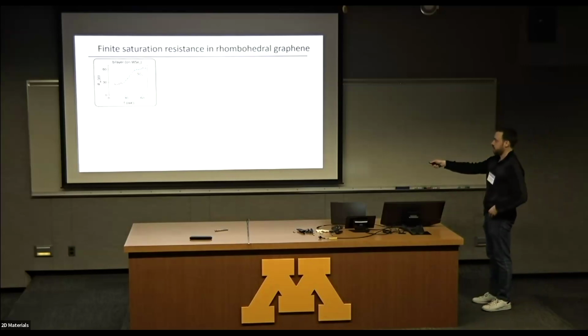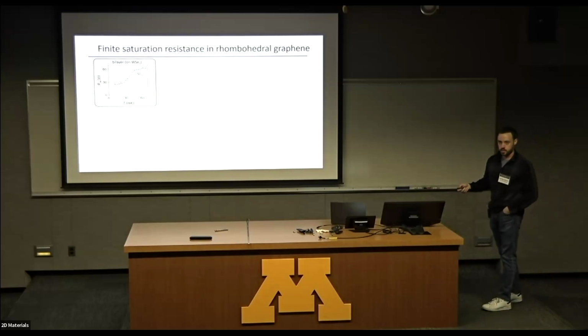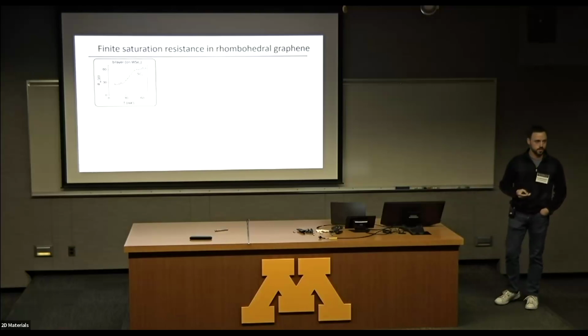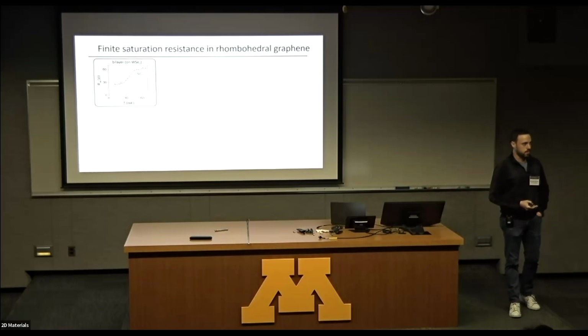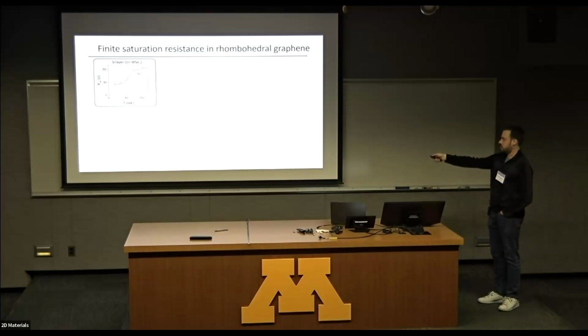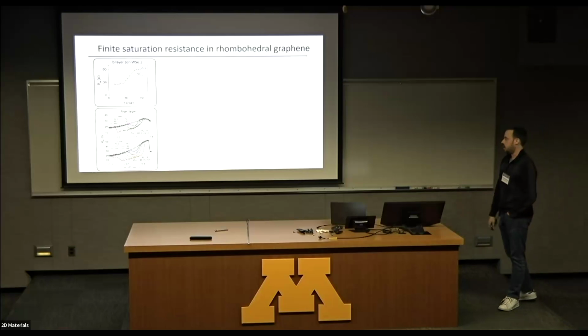There's measurements of, say, bilayer graphene on WSe2, where you have what looks like a superconducting transition, but the resistance gets stuck just below 30 ohms. This is an ultra low critical temperature, and if you've ever tried to cool electrons to below 30 millikelvin, you'll know that it's not easy. So maybe in this system, the electrons were just not getting cold enough. But we can look at other samples, and in a 5-layer sample, there's also a tendency for this not to be zero.